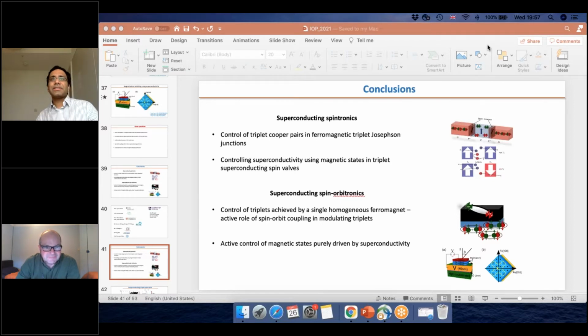Right. That's a very interesting question. How do you measure it? The easiest way to measure that would be by using a second ferromagnet, in a spin valve configuration. You can think of it as a polarizer-analyzer experiment in optics. You hold the polarizer, which polarizes the light in one direction. You take another polarizer and rotate it by 90 degrees, and you see that everything becomes dark because it blocks all the light. It's very similar. You use a ferromagnet in one direction to polarize all the spins of the electrons, and then you use a second ferromagnet; if you orient it in the opposite direction, that will block all the electron spins, and the device will be in the high resistance state. So that is one of the ways of measuring. It's not the only way, but this is the easiest way to measure the spin polarization of the current.